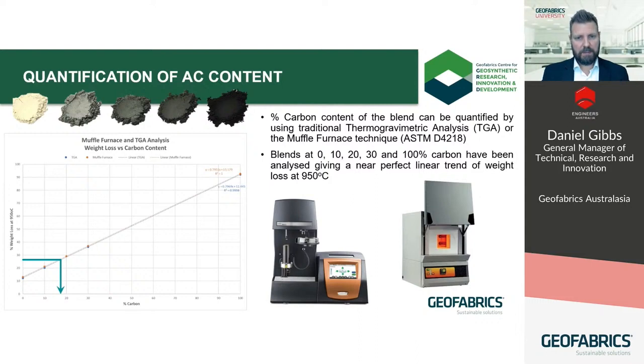You only need a gram of the blended powder to run the test. So this can be easily extracted from the GCL samples sent to the independent lab for CQA analysis, assuming the lab has a muffle furnace, of course. The result from the test is then converted to the amount of added activated carbon and also by extension the amount of dry bentonite using the calibration curve, which was developed based on a series of TGA and muffle furnace tests that we carried out using pure bentonite, pure activated carbon, and different blend percentages of each material.